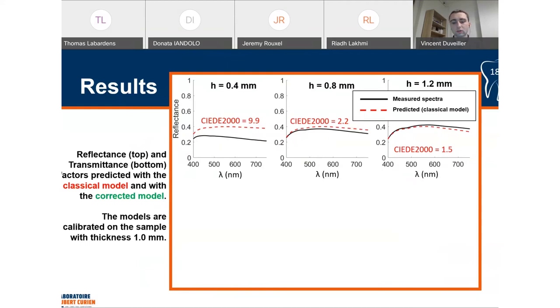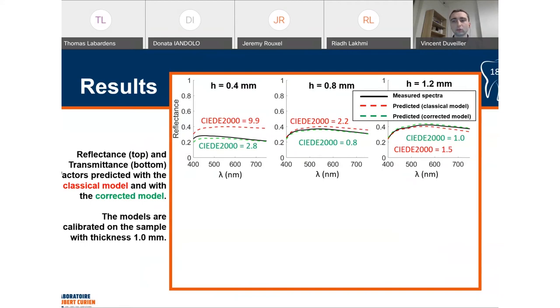However, when we use our corrected Kubelka-Munk model, so when we take into account our observations on the effective measuring geometry, you can see that the prediction accuracy has improved. For the sample with thickness 1.2 millimeter, the prediction is below the perceptibility threshold, so it's a good one. Same for the sample with thickness 0.8 millimeter. For the sample with thickness 0.4 millimeter, the prediction accuracy has improved drastically, but it's still above the acceptability threshold, so this one is not great. Now let's see the results for the transmittance factors.